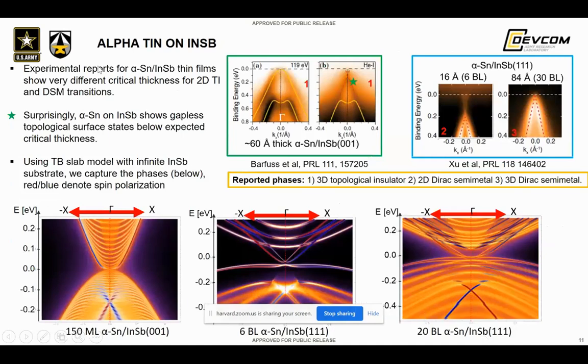If alpha tin is grown on InSb, there are some puzzling aspects which I should point out, which George found primarily. The experimental reports of alpha tin on InSb show somewhat different critical thicknesses for 2D materials, from 2D TI down to Dirac semimetal transitions. Surprisingly though, alpha tin on InSb shows gapless topological surface states below the expected critical thickness. And I'll discuss that in more detail later on.